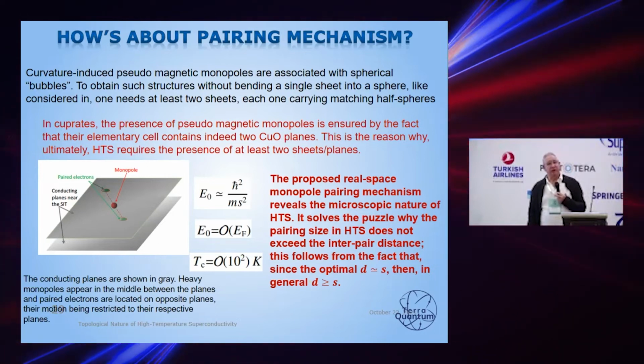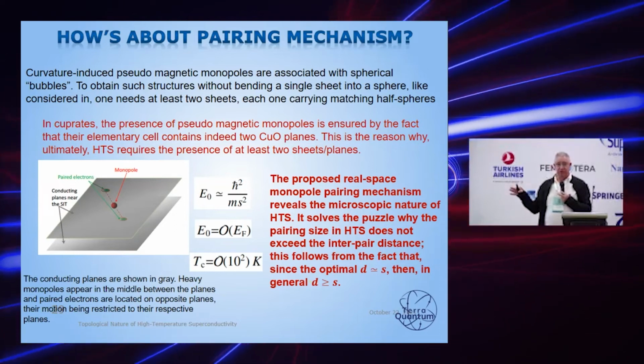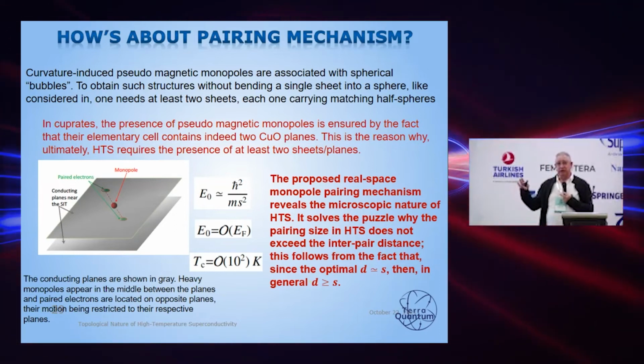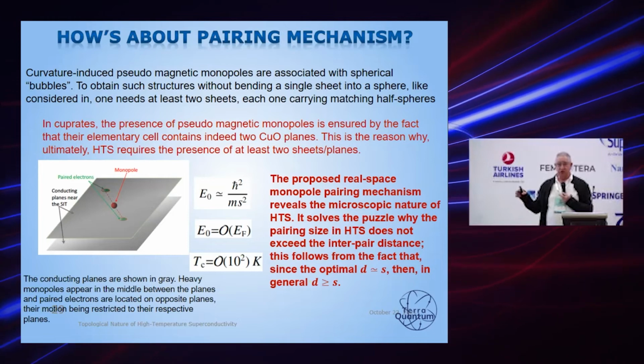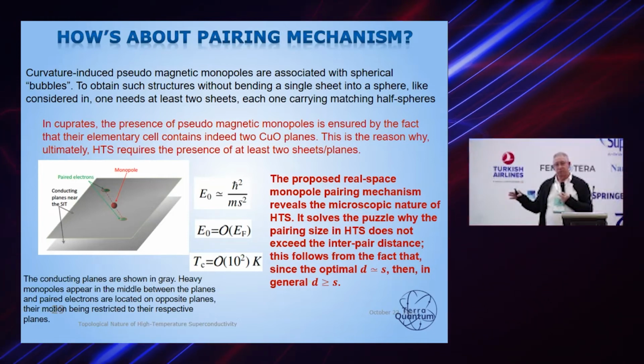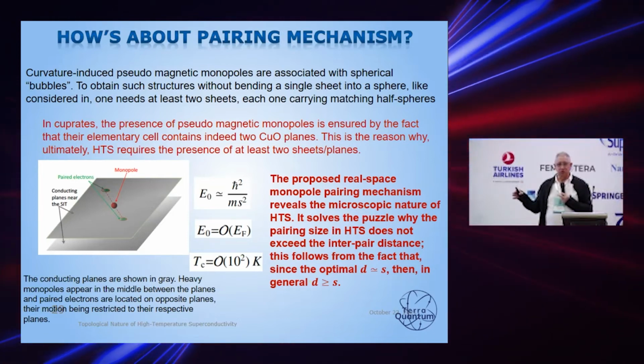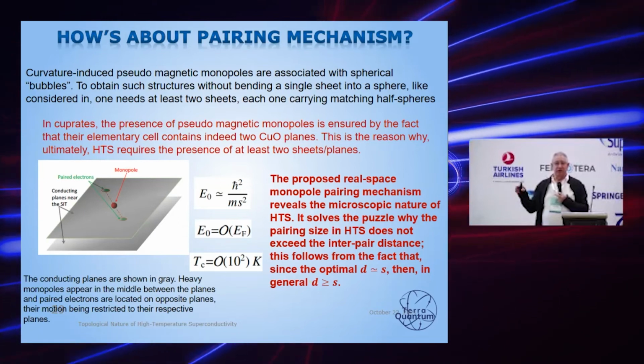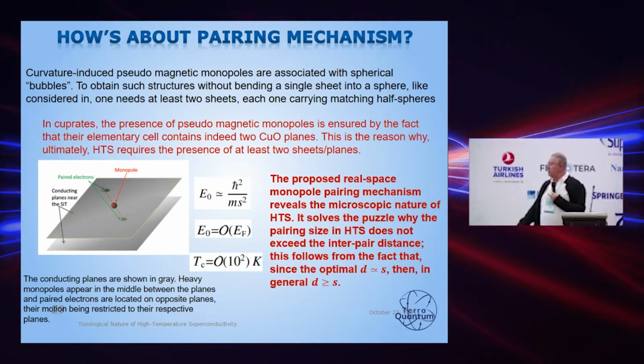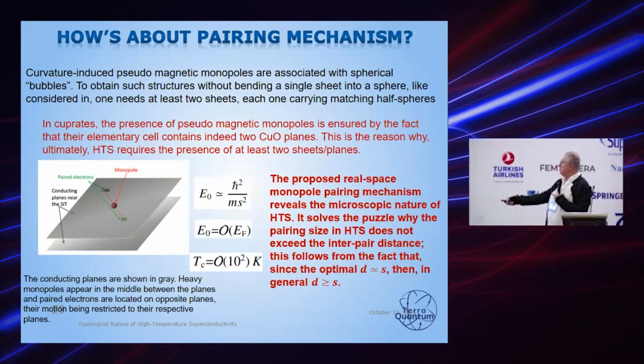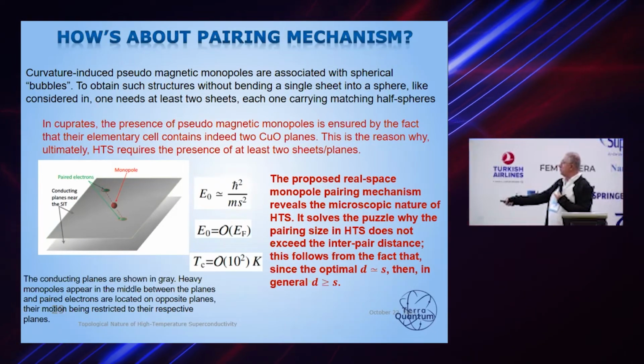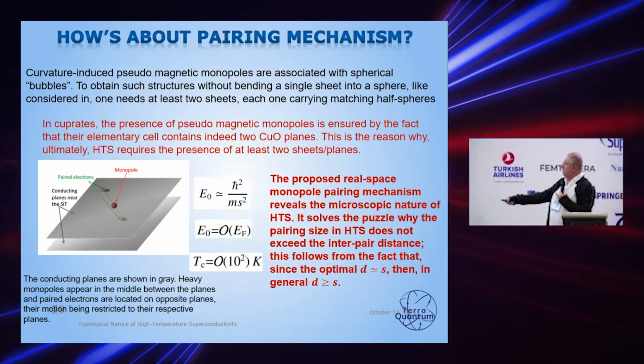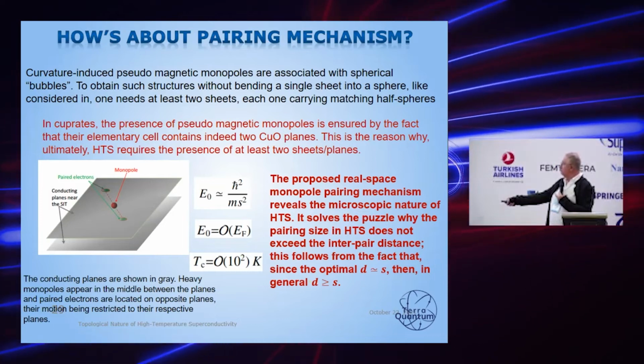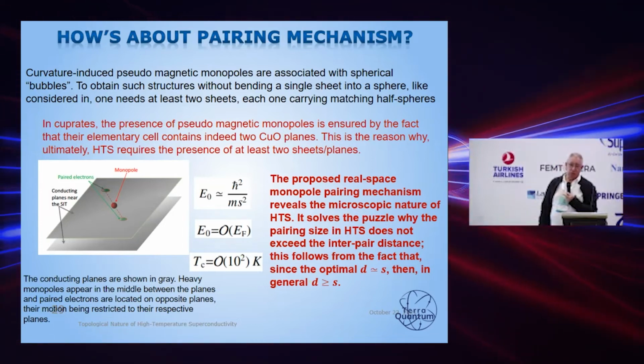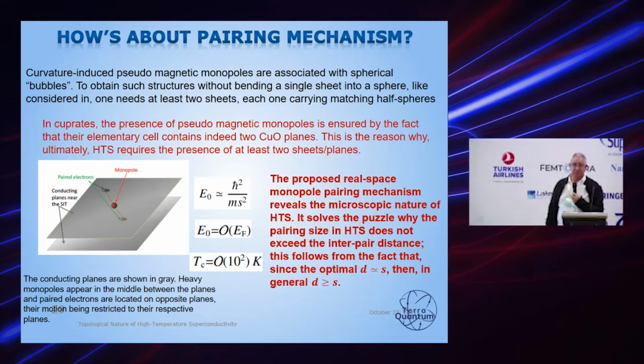And if we solve this problem a little bit more precisely, I didn't want to bother your attention with this sophomore quantum mechanics, but if you find the solution and give an estimate, then you'll find for the transition temperature that it should be at least 100 Kelvin. This is basically exactly what we see in these high TCs.